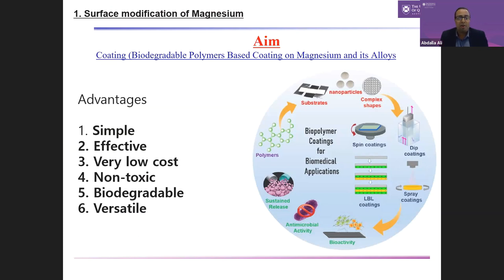They provide a simple coating on magnesium to control its surface corrosion, its early high corrosion rate. In general, the corrosion or degradation starts from the surface and is measured by length per year, depending on how much penetration can happen on the surface. If we can control the degradation rate of the surface, we might be able to depress the fast release of hydrogen